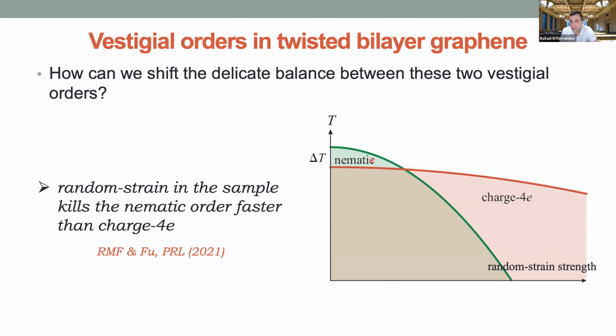We know that the nematic is very sensitive to random strain because it couples linearly with strain. We know that the three-state Potts model in the presence of random strain has no order in two dimensions. So if you have an inhomogeneous system with random strain, it is possible that you stabilize a charge-4E phase instead of the nematic phase as the vestigial phase.